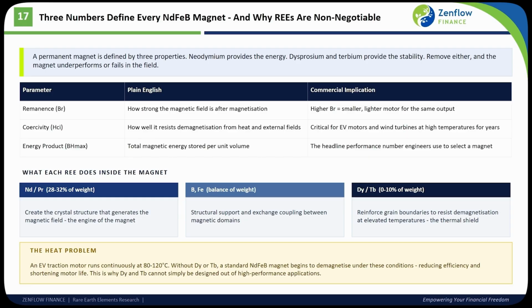They create the crystal structure that generates the magnetic field. They are the engine. Boron and iron make up the balance of the weight. They provide structural support and exchange coupling between magnetic domains, essentially the chassis. The dysprosium and terbium together make up 0 to 10% of the weight, depending on the application. They reinforce the grain boundaries of the crystal structure to resist demagnetization at elevated temperature.